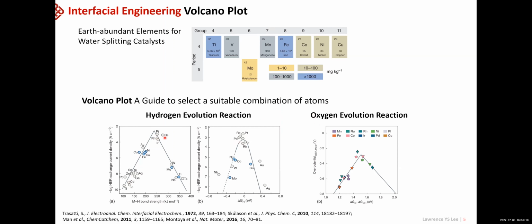On the top of the volcano plot, if you just look at the single metal species, they are usually occupied by precious metals like platinum or palladium. So the goal is to tune these earth-abundant transition metals so that they can climb up this volcano plot to the center of it. That means they are not binding the intermediate too tightly or too loosely, so that they have optimum binding energies for the reaction, and can efficiently catalyze the water splitting reaction.